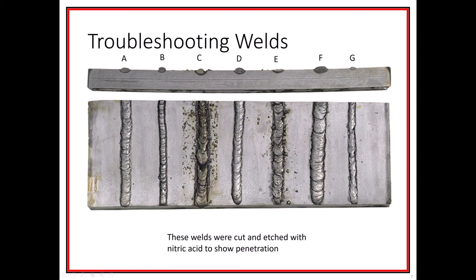If you go too fast, or maybe your electrode isn't hot enough, the bead might stick on top like you have right here and not penetrate deep enough. If you have it too hot, you'll undercut like here at C, and you'll get all kinds of spatter all over the place. You could also see that there was an inconsistent amount of travel speed taking place here. You get a little slow here, a little fast here.